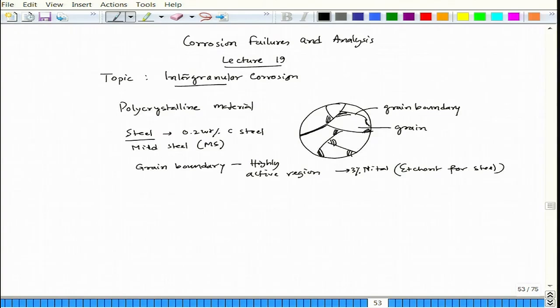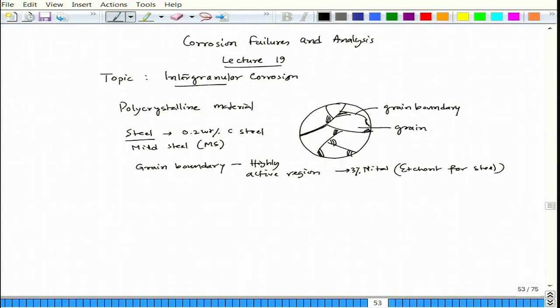There are two types of etching: immersion etching and swab etching. In swab etching, you take a cotton block, soak it with nital, and after preparing a scratch-free mirror-like surface of the steel, you rub that cotton ball soaked with nital over it and watch for the change in colour. Once you see an overall uniform grey colour, you immediately put it under running water, wash it with alcohol, dry it, and view it under the microscope — and it looks like this kind of microstructure.